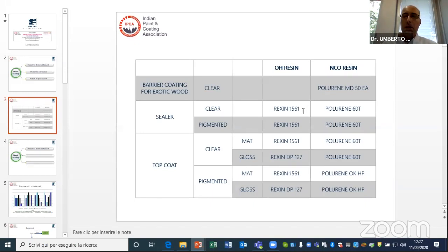As you can see, only 2 base resins and only 2 hardeners for all the system. Polurene 60T is a hardener that is very versatile. It is a hardener at 60% solids in butyl acetate. It is a product that allows a very good balance between fastness of drying and the pot life that can be warranted. And it also allows very good compatibility with different systems and components that we can introduce inside our system, like nitrocellulose, like vinylic system, like CAB solution, and so on.